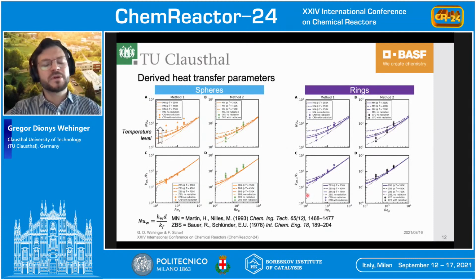So the derived heat transfer parameters represented as Nusselt wall and K effective by K fluid look like that. Dots are the scenario CFD without radiation and stars are with radiation. And I compared that with typical correlations for Nusselt wall by Martin and Nilles. And for both cases, we can see that Martin-Nilles is highly underpredicting the thermal radiation effect, especially for higher Reynolds numbers and higher temperature levels. On the other hand, the K effective from Zehner-Bauer-Schlünder looks, at least for method 1, pretty good, I would say. Method 2 somehow gives different values, but I will come to that later on.